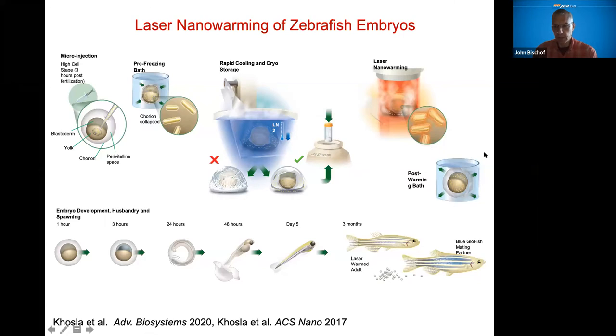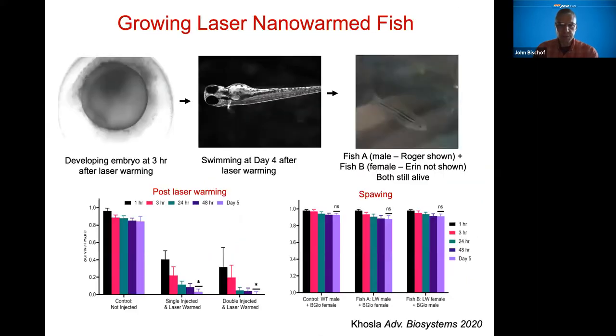And then we actually have a post-warming bath. This pre-freezing bath and this post-warming bath were actually critical innovations in our method. And then we were able to see this growth and hatching over time, and actual growth to adulthood, and mating and spawning as normal. And so that's what this data is showing. We actually had several of these fish, several of them are still alive. And the percentages are quite low, but none of these bars existed in the past for any zebrafish prior to this work. So there was nothing at 1 hour, and certainly nothing at day five or going to adulthood. So these adults then were able to spawn very similar to control. And that's what we just published in Advanced Biosystems.